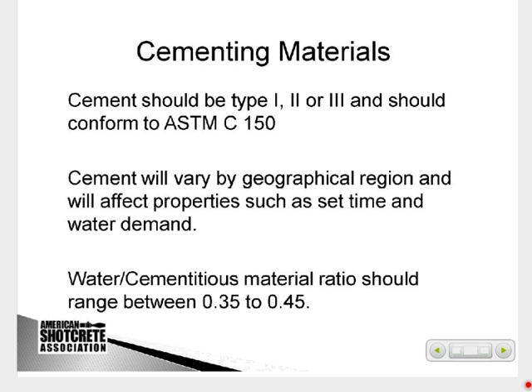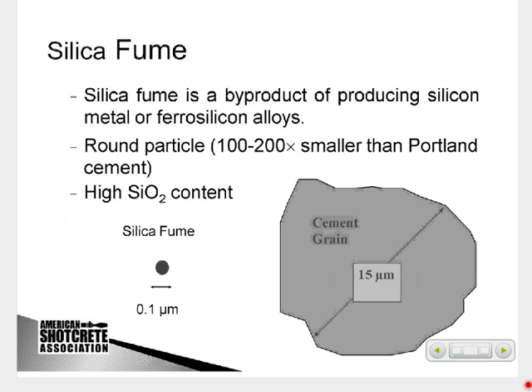That shotcrete is in many ways self-limiting. If it's too high a water-cement ratio, it doesn't hang on an overhead section, and it tends to slough off more easily on a vertical section. So we'll find with dry mix, you typically range from a 0.35 to maybe 0.42. Wet mix may go as high as 0.45. If it's over that, it just is not able to be shot and stay in place.